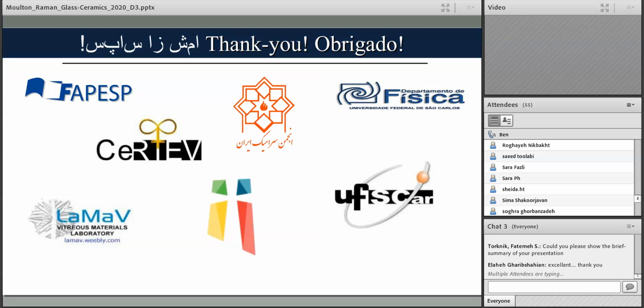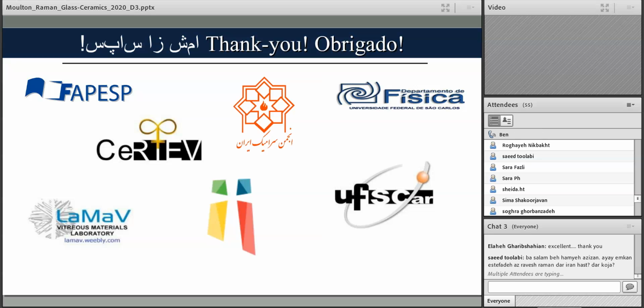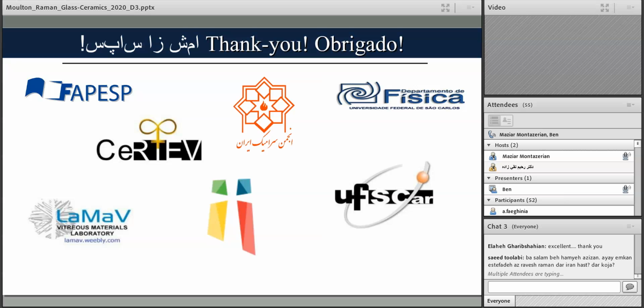The only caveat or caution I would recommend is that you have two effects. It's not just the bonding, which the bond strength certainly affects the vibrational frequency, but you also have the ability to polarize that bond as well. So you have to be a little bit careful of these two effects. But otherwise, in general, absolutely you can say what you're saying.